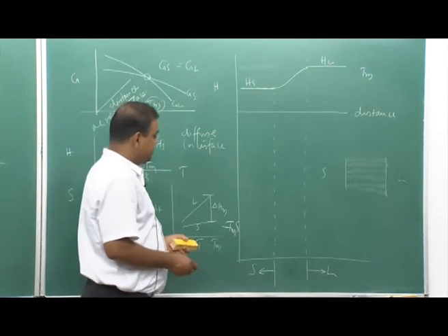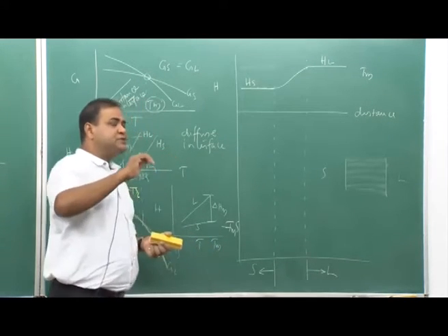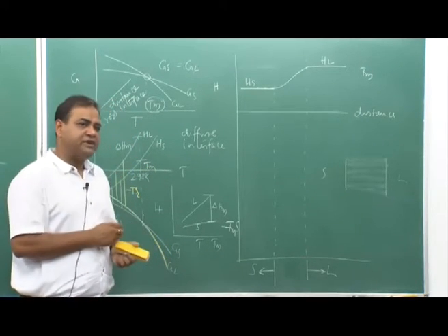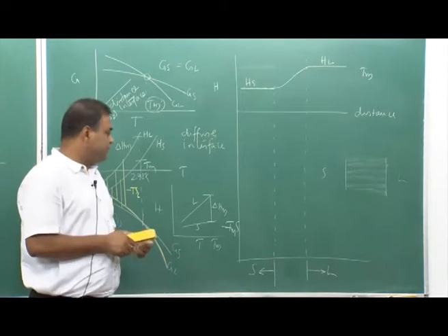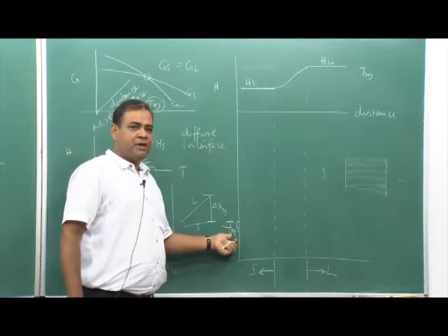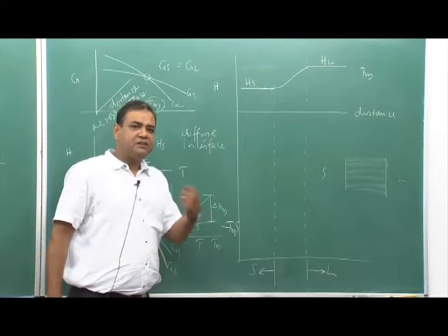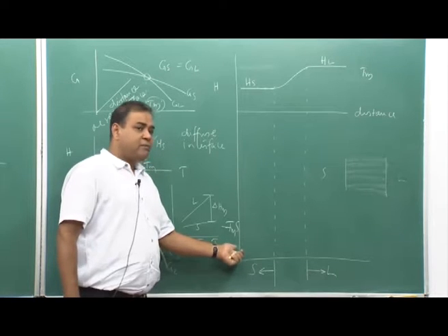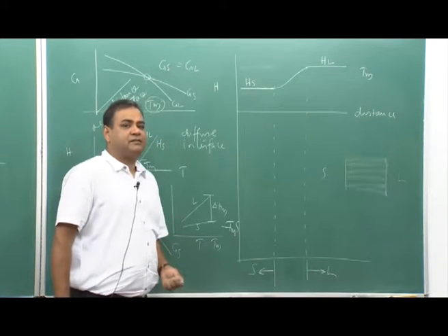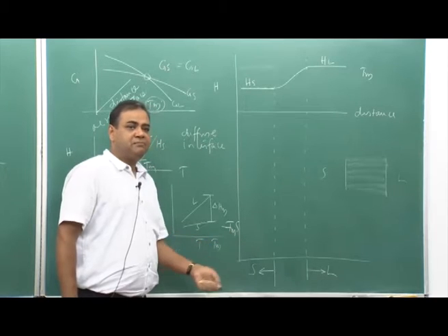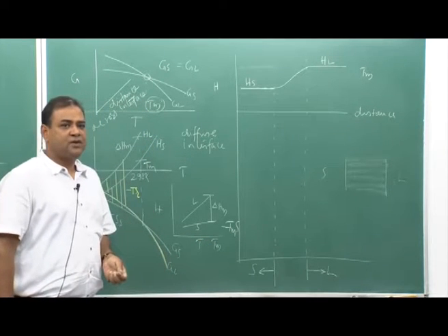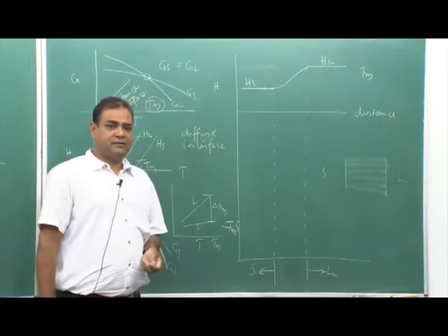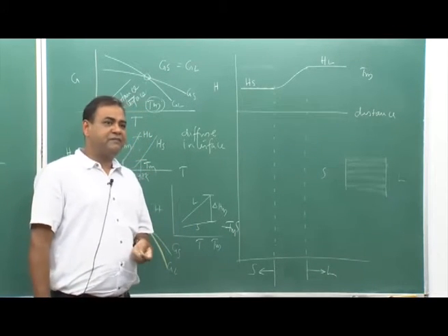Since we know that the solid entropy is lower than the liquid entropy, if we multiply with T m, both would increase of the order of T m. But if we put a minus sign, the T s term for solid would be more than the T s term for liquid, because we have considered a negative sign there.